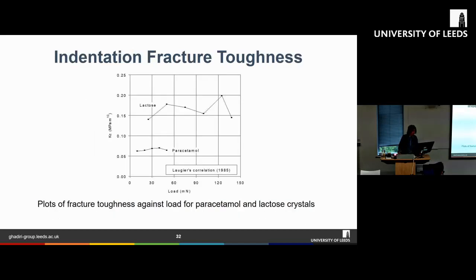If you now plot the fracture toughness measured against the load, you can see that here we have two different materials, lactose and paracetamol. Lactose has a much higher fracture toughness compared to paracetamol. Another interesting thing to note is that load has very little effect on fracture toughness. As you can see, if you increase the load, the fracture toughness remains almost constant.